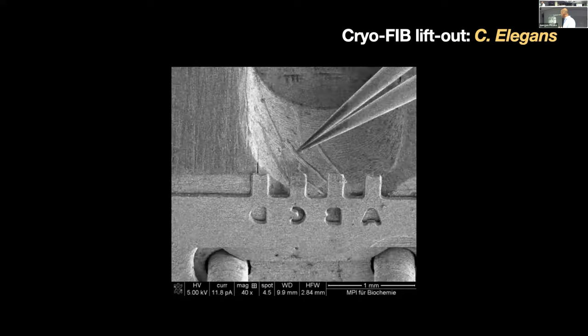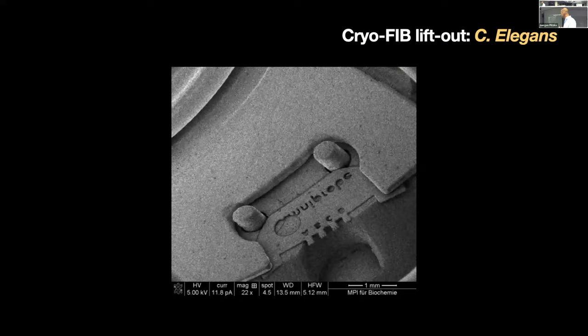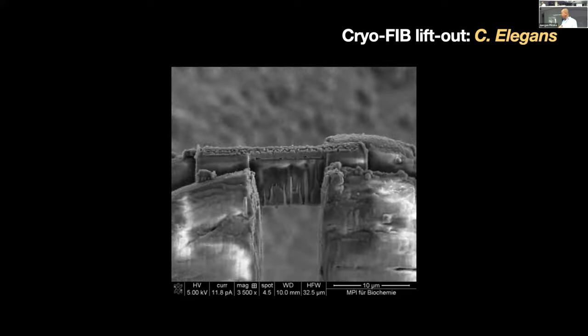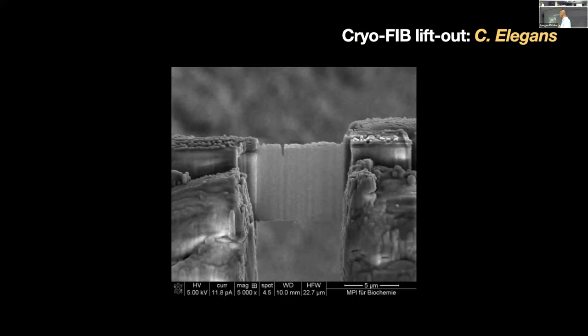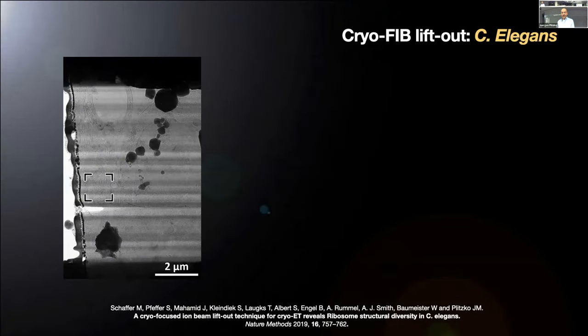You place it into this slot grid, which we modified a little bit because our lift out sections are much smaller than the material science sections. And then in the end, you thin further until you get electron transparency. You see that little crack at the far end of that lamella, and that you will see in the next slide in the TEM overview again.